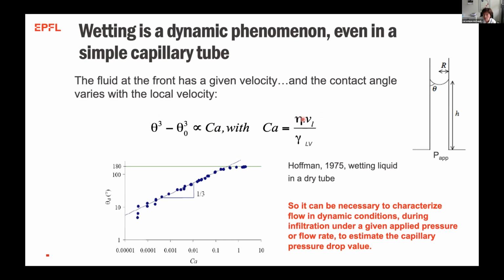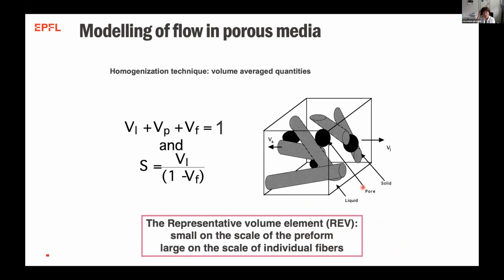The capillary number is a dimensionless number: the viscosity of the liquid times the velocity of the liquid over the surface tension of the liquid. So if you increase the capillary number, which means for the same liquid you increase the velocity, then the dynamic contact angle varies from a static value up to something that can be super high if you go super fast. In our case, because the viscosity is generally quite high, we need to worry because this capillary number can be quite high. So it might be necessary to characterize flow in dynamic conditions to estimate the capillary pressure drop value in realistic cases. For doing this, you need to know a bit more about what's happening during flow.